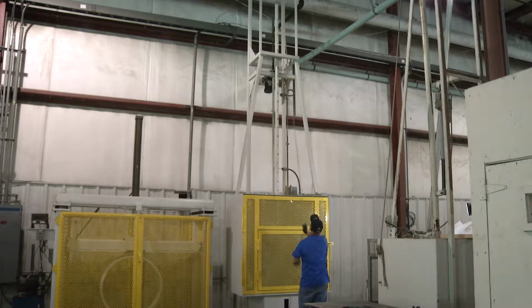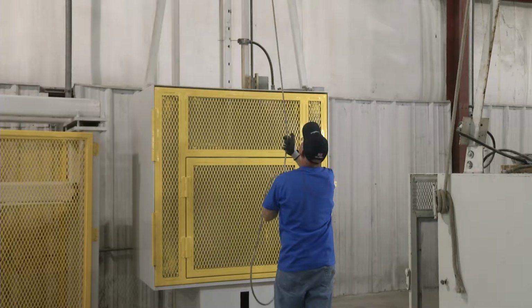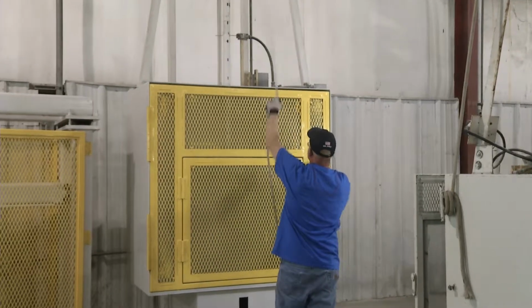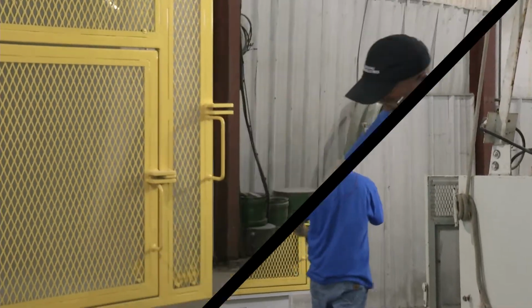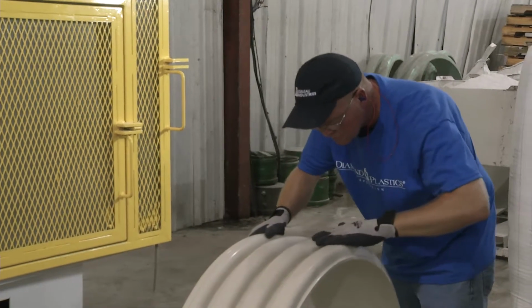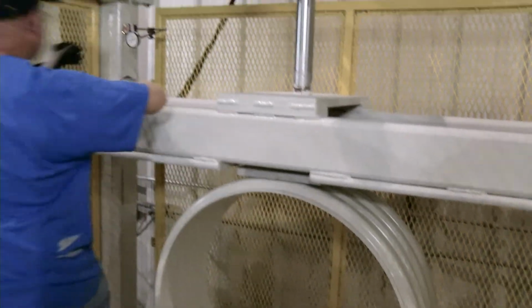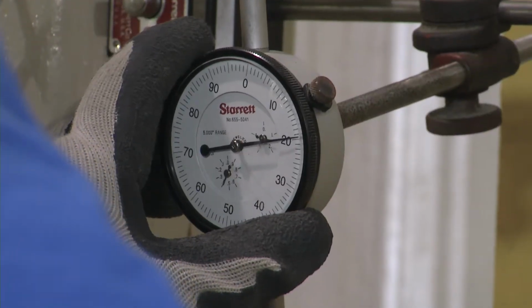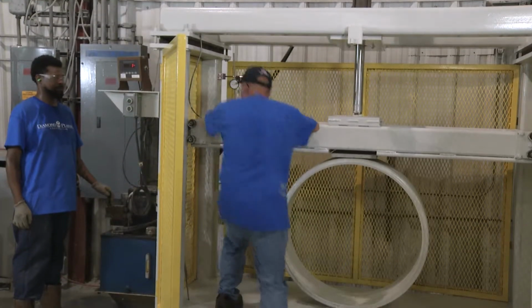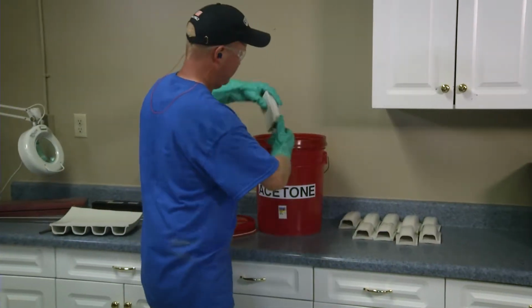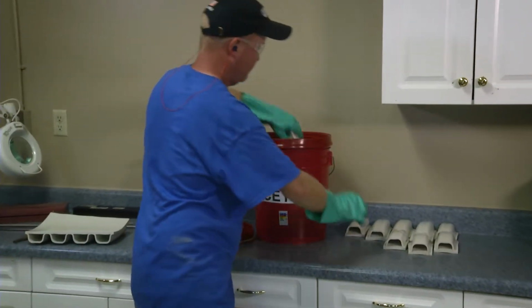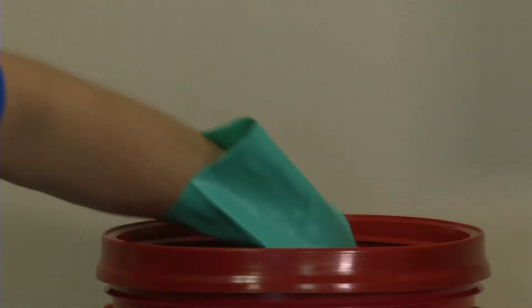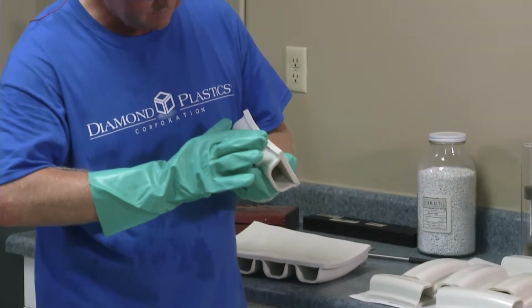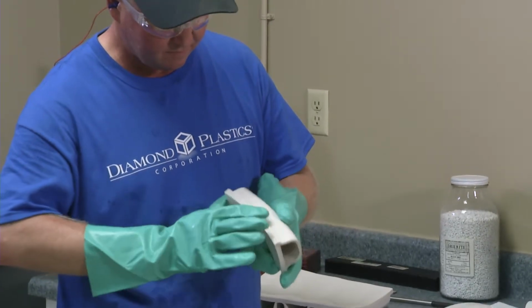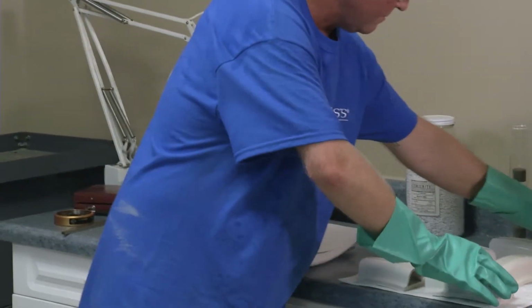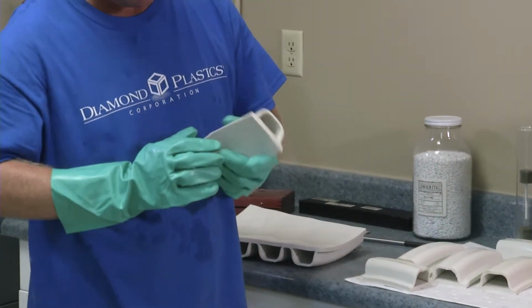An impact test is completed in which a 20 or 30-pound tup is dropped from a set height to assure proper extrusion was achieved. Any cracking or splitting would signify a failure. Pipe stiffness verifications are conducted to assure it meets the minimum requirement of 50 psi in accordance with the industry standard. A fusion test is performed by placing a properly prepared sample into an acetone immersion bath for 20 minutes. When removed, the technician looks for flaking or lifting of the PVC, which would signal a failure and suggest an improper material fusion during the extrusion process.